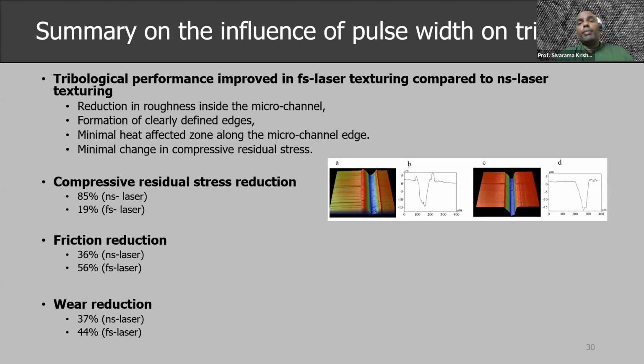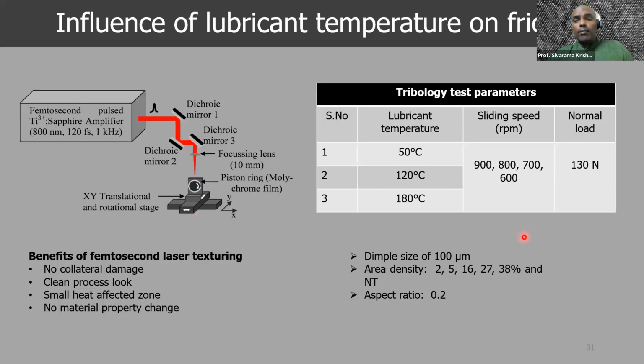So one can conclude that it could well be preferable, especially if one is going to establish a new system or a new industrial line, to use femtosecond pulses, which are becoming more and more robust. The laser systems are becoming more robust, and their cost is also reducing. It may be better to choose a femtosecond laser because not only is the friction reduction better and wear reduction better, but residual stresses on these materials are also much more reduced in the case of femtosecond laser interaction. So this is an interim summary of Maran's work.